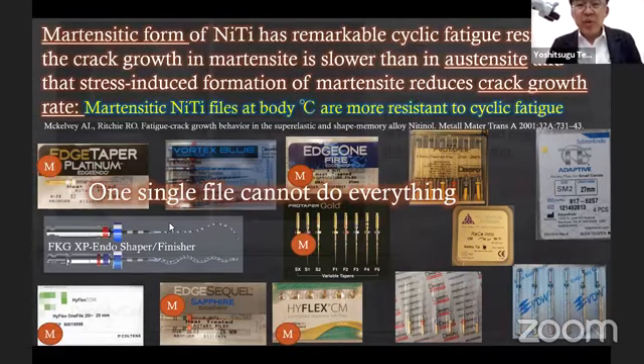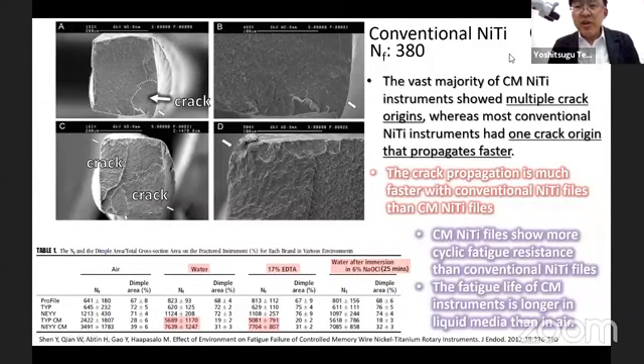And this study also showed that crack propagation here is much faster with a conventional nickel titanium instrument than with a controlled memory nickel titanium instrument. As you can see, if you have only one crack, it will propagate much faster, so without symptoms, you will fracture the instrument. But with the CM instrument, you have several cracks, but they propagate very slowly. So you can see the deformation, or you can even see the cracks created on the instrument surface under the microscope. Then you can discard the instrument.